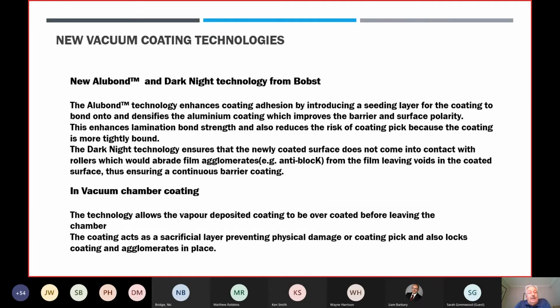And you say, well, it can't be a liquid coating. No, it's not. It's a coating that's applied and then it's either hit with electron beam or plasma to cross-link that coating. And that coating then acts as a sacrificial layer, preventing physical damage or coating pick. And it also locks coating and agglomerates in place. So if you have an agglomerate on the film that may have been susceptible to being pulled off when the roll is unwound, it can't, because this coating locks it into place.